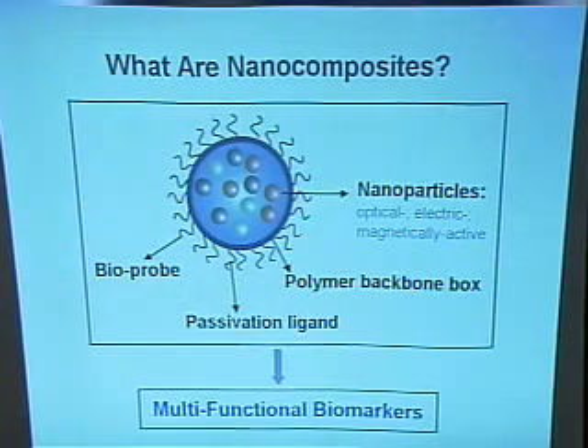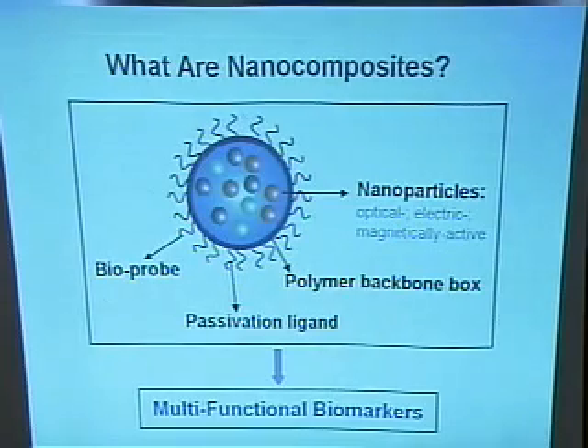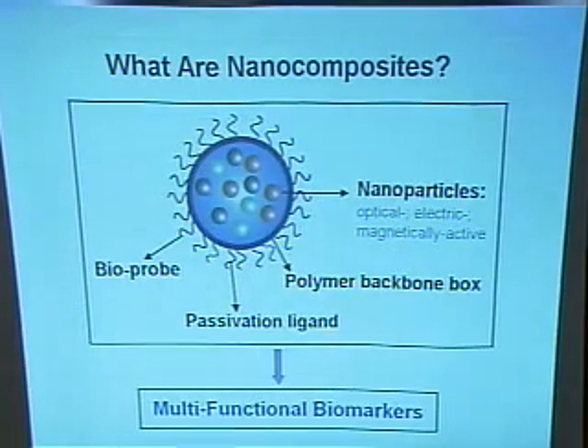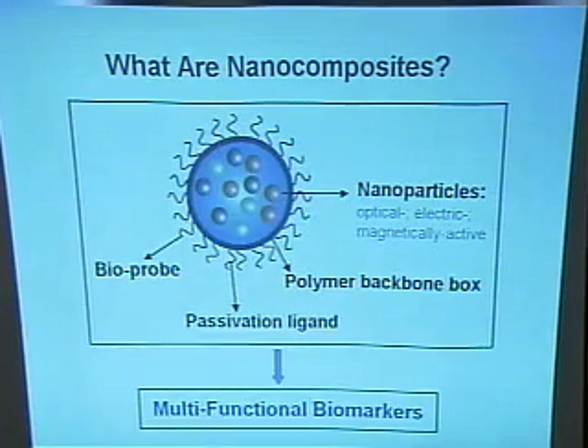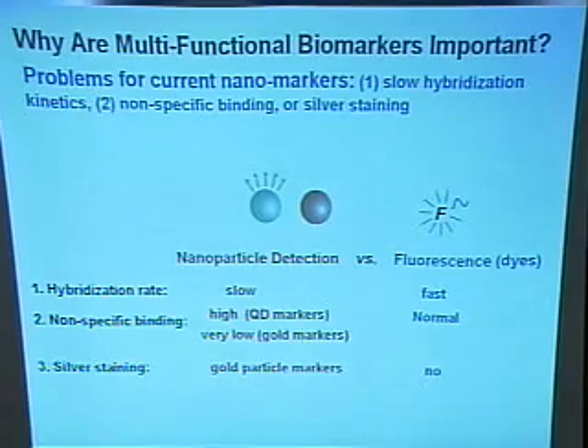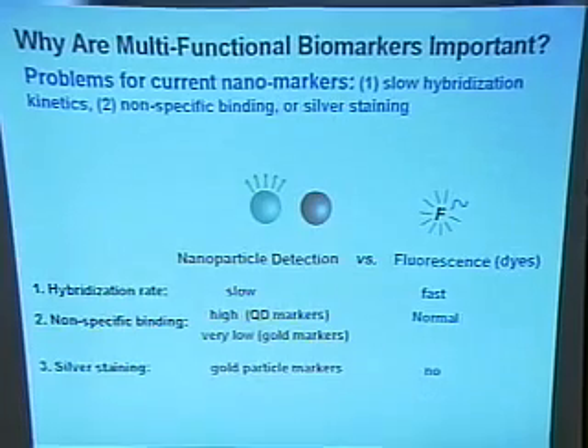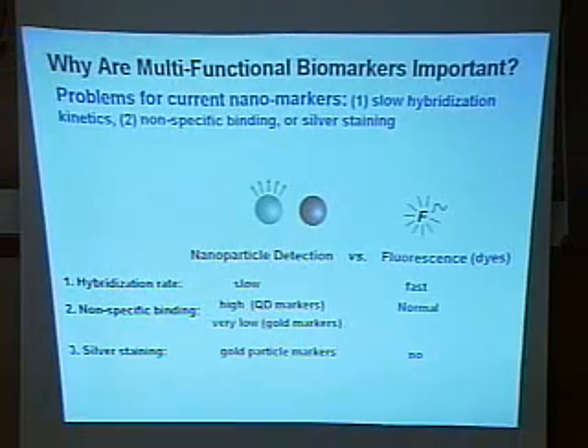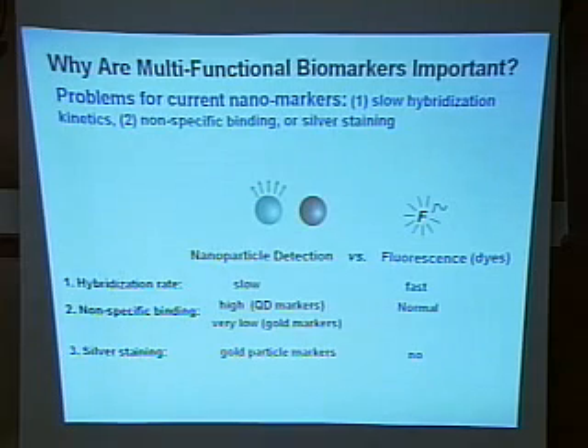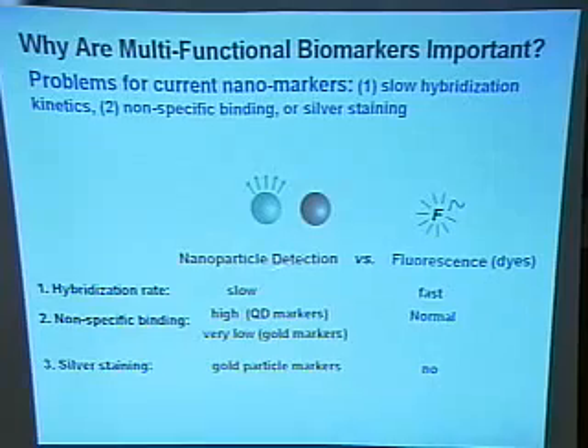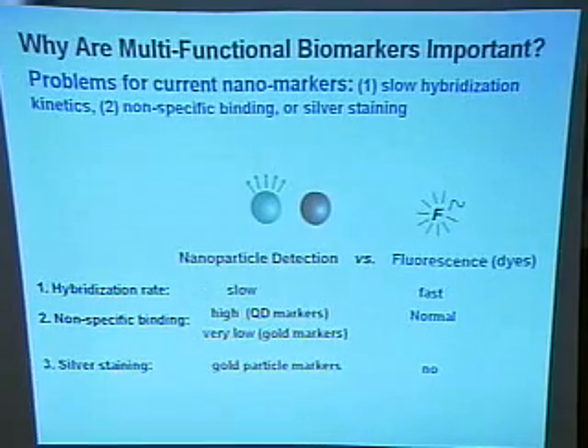And the question is, why is such research important? So they can solve the current problem of using biomarkers to do detection. I already taught you that nanoparticles have a bunch of advantages, but they also have some disadvantages. The first is slow hybridization kinetics. Compared with the fluorescent dye, it's really slow. Fluorescent dye can do it in half an hour. We have to use a few hours, say at least 2 or 3 hours.